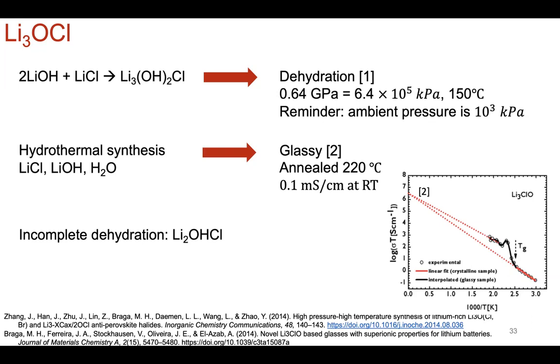And in terms of measuring the ionic conductivity, it's pretty competitive to start off with at 0.1 millisiemens per centimeter at room temperature, right? We're aiming for 10 millisiemens per centimeter, parity with liquid electrolytes, conventional carbonate base. So there's room for engineering higher ionic conductivity, which is promising, but one has to really caution what one is measuring. So, are you really measuring the ionic conductivity of Li3OCl, or are you really measuring Li2OHCl, right? And the tiny bits of moisture that's left in due to incomplete dehydration can really dominate the ionic conductivity and the values that you measure from these types of compounds. And this is just from experience from a lot of studies on these types of compounds.